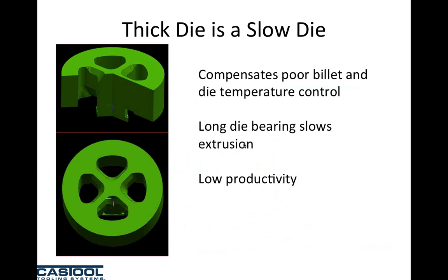This is a look now at what is a rather thick die with rather small ports. Typically these are used to compensate for poor billet and die temperature control. Very often, last week I was with 7 different extruders through Southeast Asia, and all the die correctors want thick dies with long bearings. The reason is they do so much die correction because of temperature instability that they need something to work with.